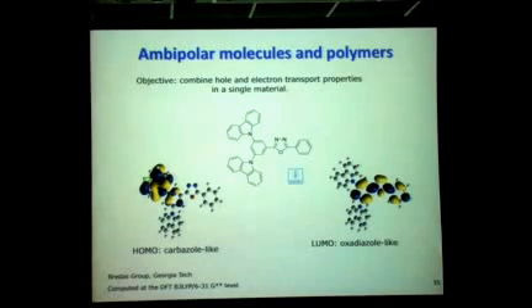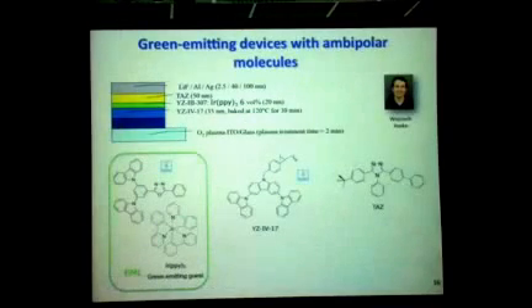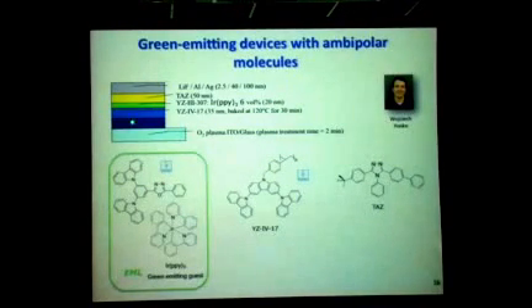You can see from quantum chemical calculations done in the group of Jean-Luc Bredas that the HOMO orbital is actually located on one of these carbazoles, while the LUMO orbital is located on that oxadiazole. To illustrate the nice properties of these molecules, here's a device example where we start with an ITO-coated glass treated with plasma to increase the work function.